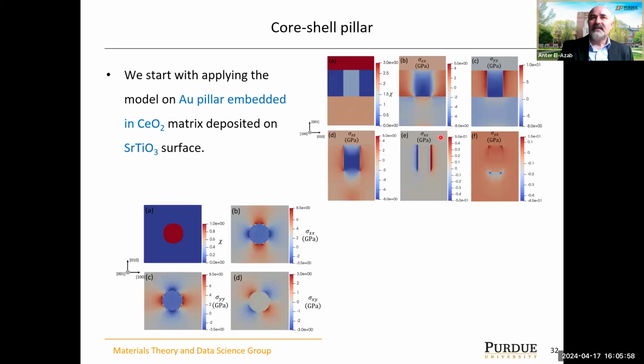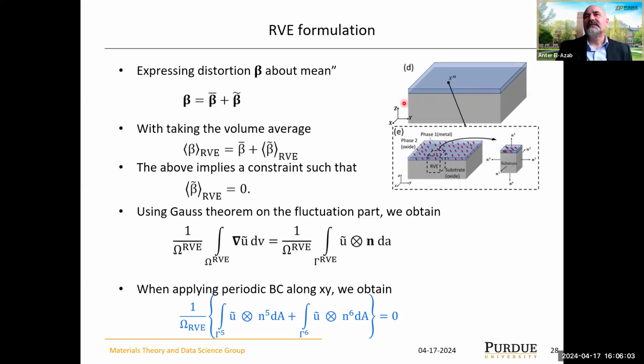So I'm going to skip the FFT details because it's standard, and show you how the strain looks like in the heterogeneous material system. First of all, before we get to this, I'd like to just draw your attention to the fact that this film system is infinitely extended, or not infinitely, but extended in the plane of this film to large sizes. On top of the film, there is empty space or vacuum or something like that. This problem does not lend itself to fast Fourier transform solution in the 3 dimensions. We can do periodicity or assume periodicity only in the 2 directions containing the plane of the film.